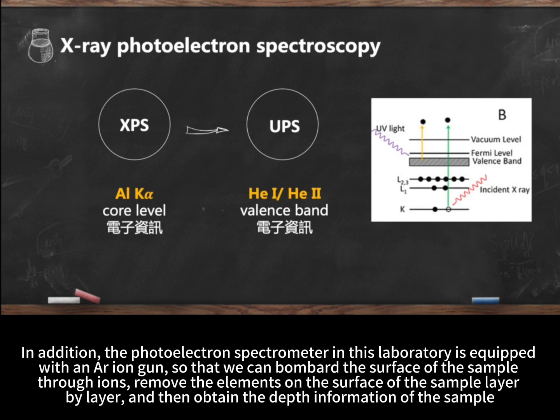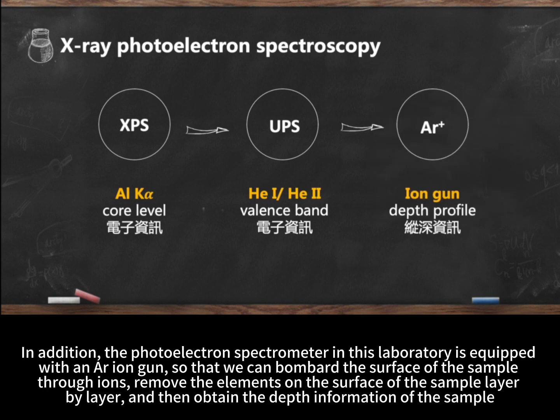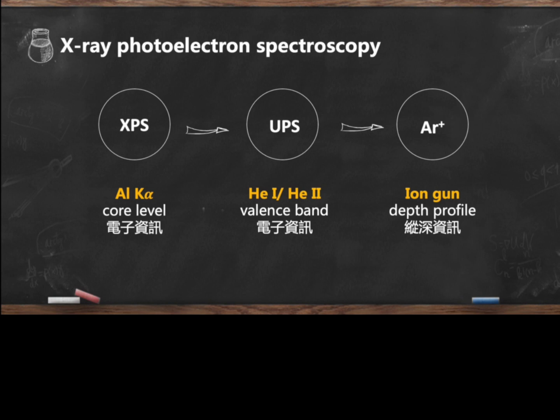In addition, the photoelectron spectrometer in this laboratory is equipped with an Ar ion gun, so that we can bombard the surface of the sample with ions. Remove the elements on the surface of the sample layer by layer, and then obtain the depth information of the sample.